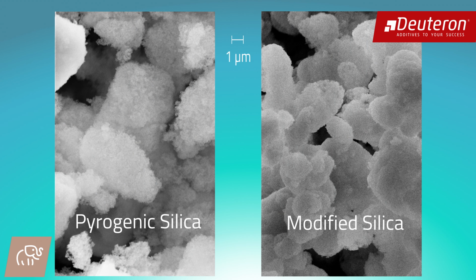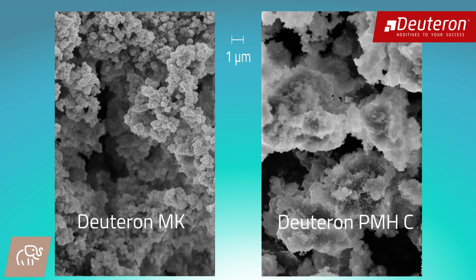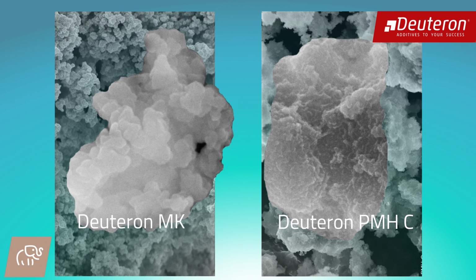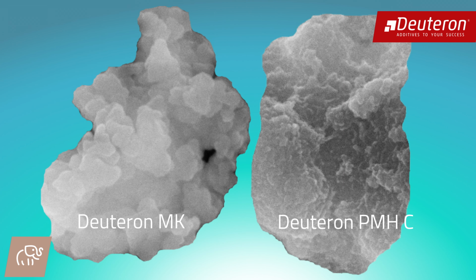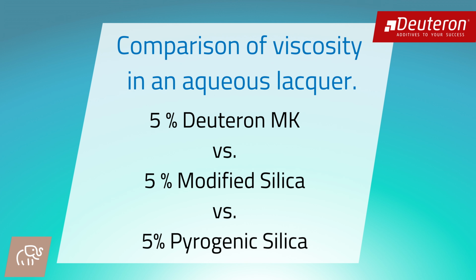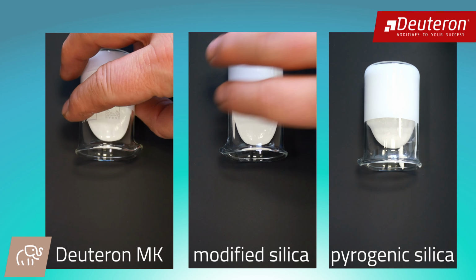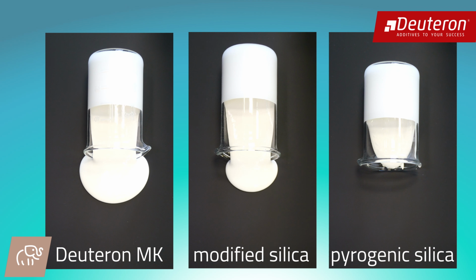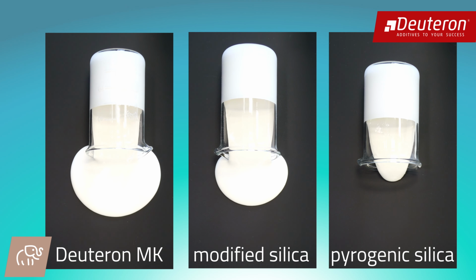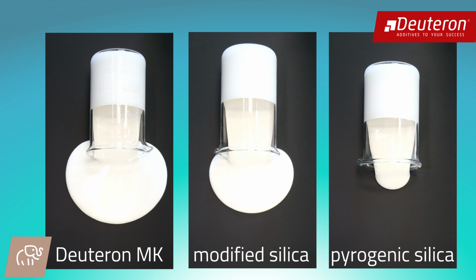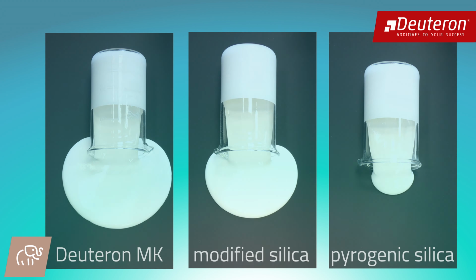Silica-based matting agents have a highly amorphous particle structure and therefore strong thickening effects. Our matting agents have lower impact on the viscosity and good mechanical resistance. Deuteron PMH-C has another particle shape. It is more compact and has even lower influence on the viscosity than the Deuteron MK. In comparison, silica grades have a more amorphous structure. This is the reason for the high impact on the viscosity. Due to the special particle surface of the PMH-C, the influence on the viscosity is lower than with silicas. This means that higher dosages are possible.